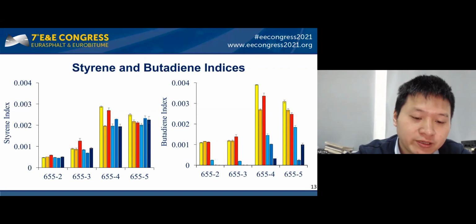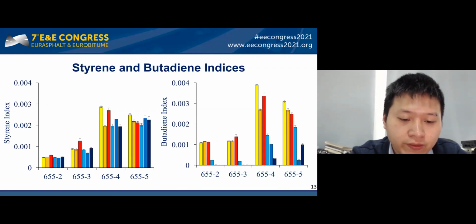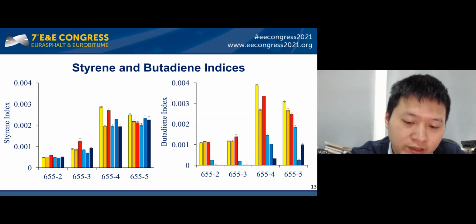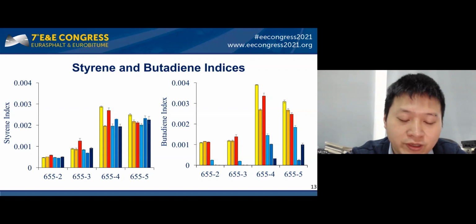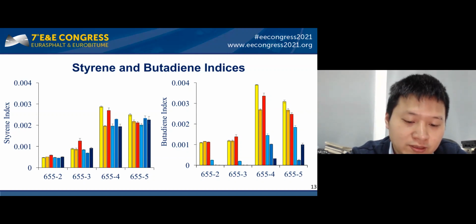The findings for the SBS integrity were not encouraging, as we were able to recover most of the styrene, but the butadiene functionality saw a precipitous decline, and after only 5 years of service, the butadiene group index was reduced by anywhere from 25 to more than 75%. This shows that after 8 to 10 years of service, the effect of the polymer is almost gone when it is most needed.